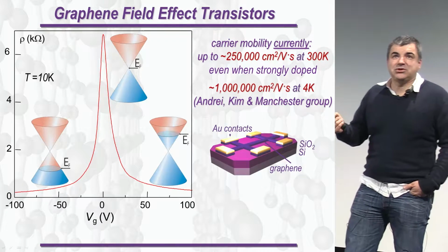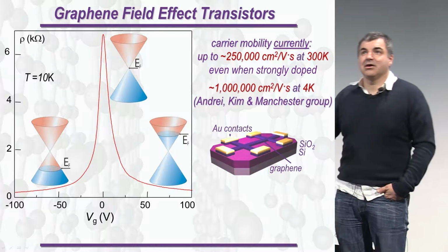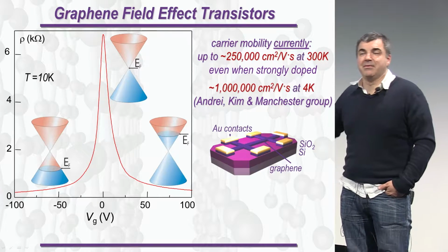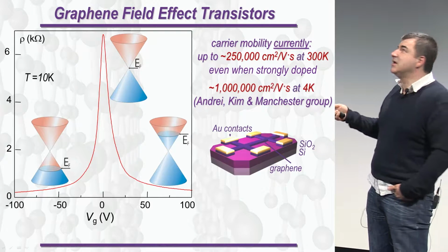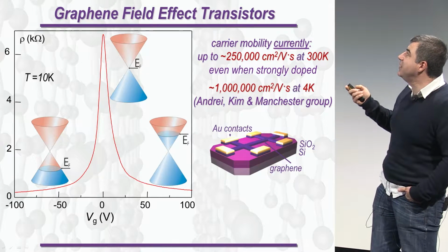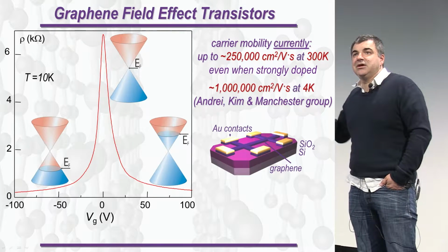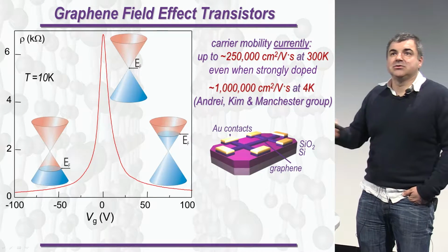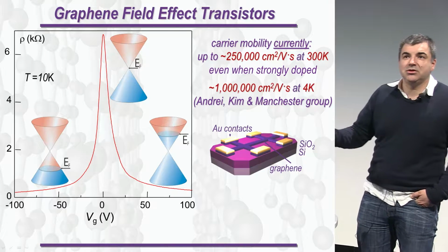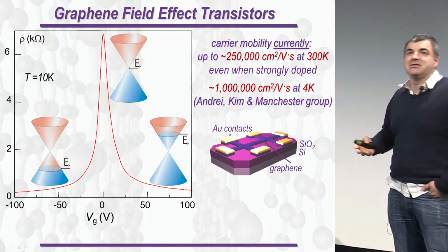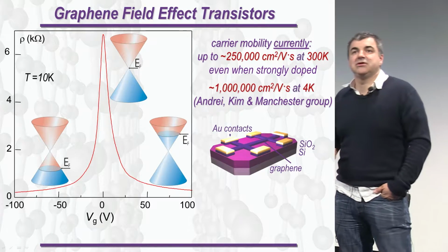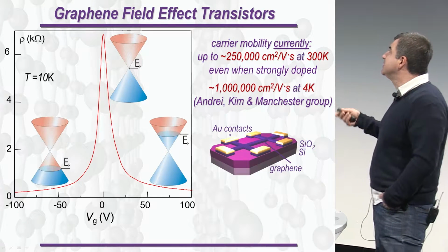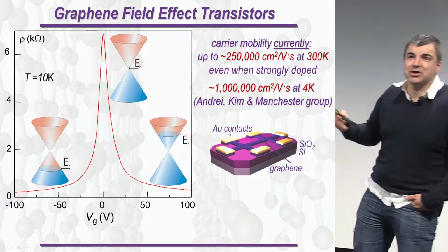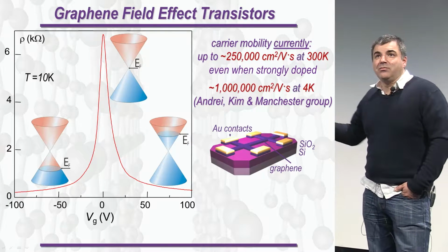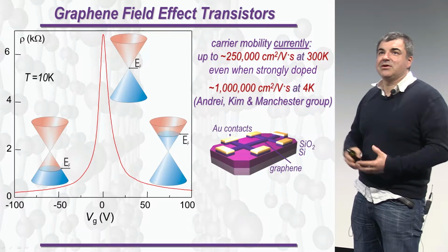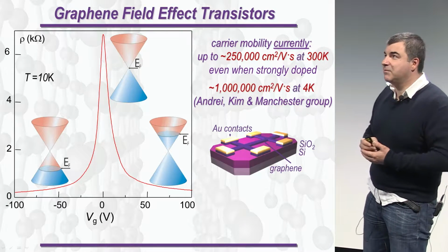The parameter which tells you how fast your electrons move across the crystal is called mobility. The figure of merit for graphene would be 250,000. At low temperature, it's even higher. If you compare it to silicon transistors, which are in your computers, it's 1,000. The best HEMT devices, which are in your mobile phones, is 50,000. So graphene is already doing much better. And that's all because of its hexagonal symmetry and the very specific electronic band structure.